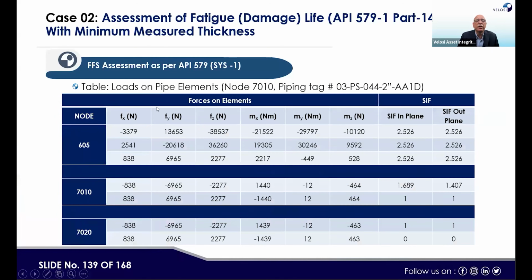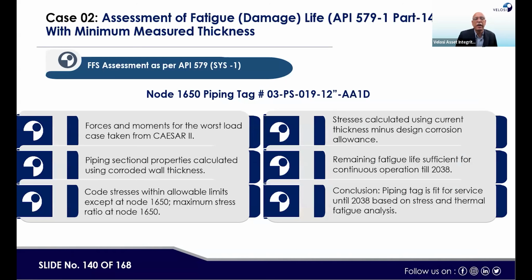Now, if we see here the table of loads on piping elements, node 7010, piping tag number, you can see the various loads, like SIF, for example, in-plane 2.52, and the SIF out-of-plane ratio shows more or less the same, and these are the moments and the forces. Now node 1650, piping tag number, forces and moments for the worst load case taken from Caesar II, piping sectional properties calculated using corroded wall thickness, then code stresses within allowable limits except at node 1650, maximum stress ratio at node 1650. Then stress is calculated using current thickness minus design corrosion allowance, remaining fatigue life sufficient for continued operation till 2038. Conclusion: piping tag is fit for service till 2038.